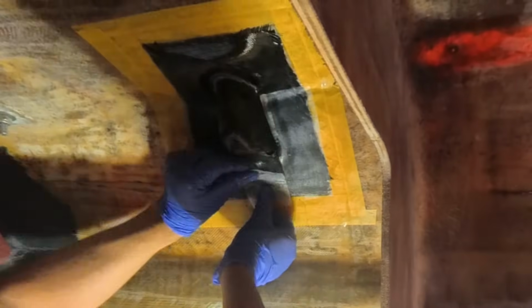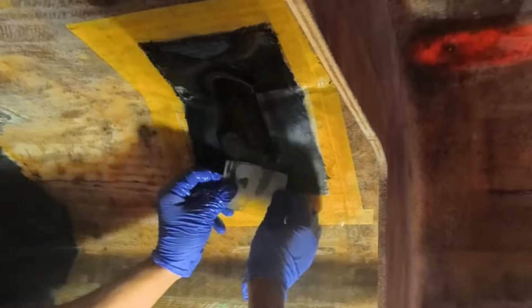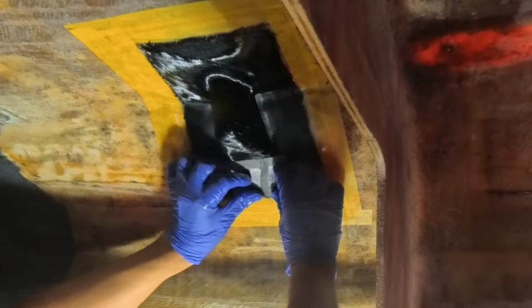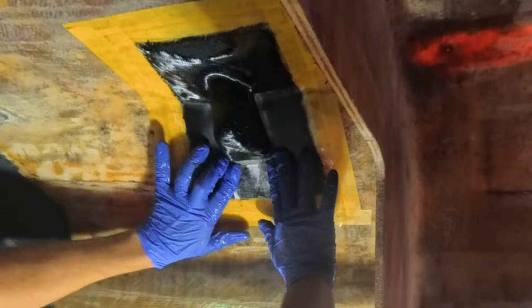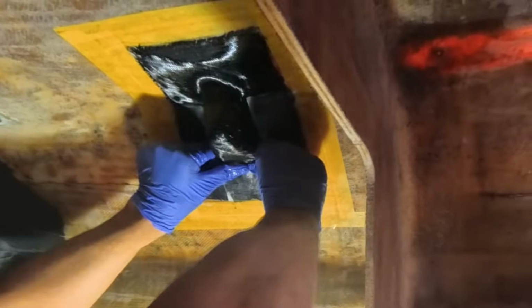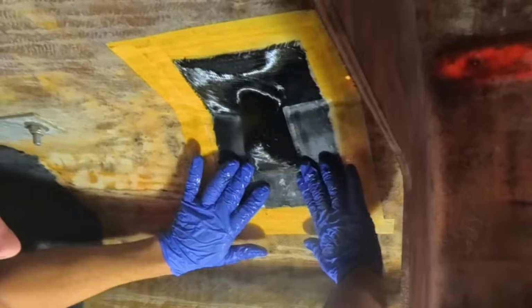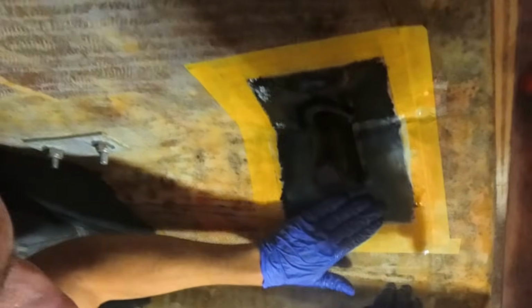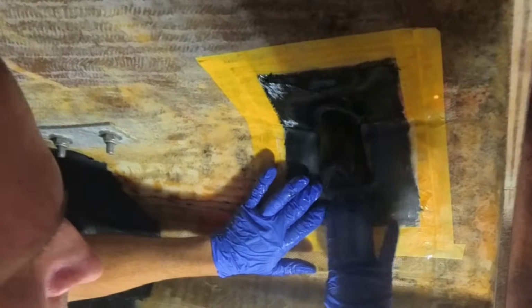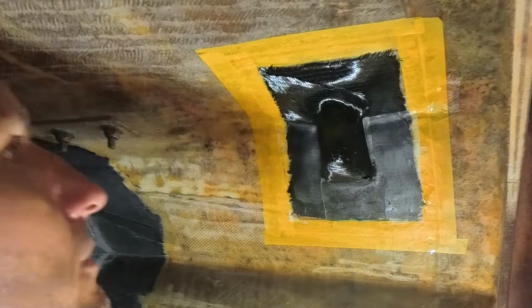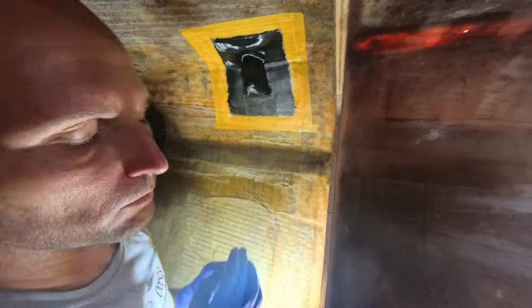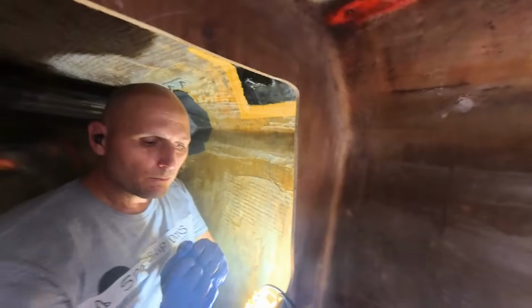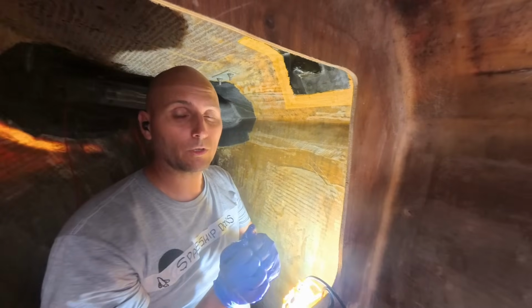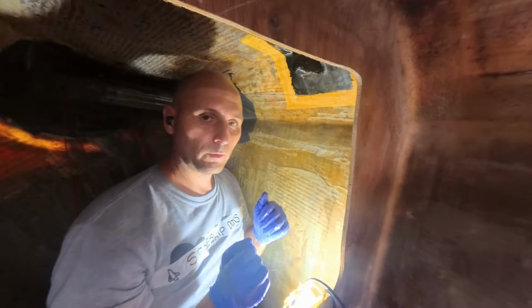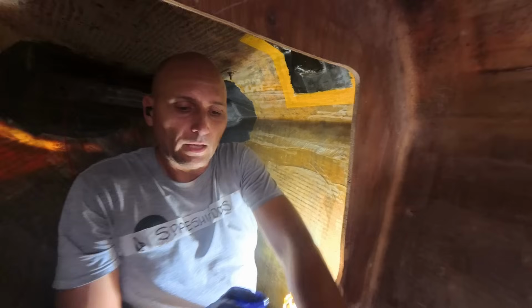It's not best practice. It is definitely not best practice, and there's heaps, and when I mean heaps, there's heaps of literature in regards to peel ply, surface finishes, and preparing them for secondary bonding. And I know a fair bit about this because it was something I was involved in a little bit, and the aviation industry was talking to us a fair bit about it once upon a time, so it is an area I do know fairly well. Simple way to put it, peel ply, whether it's nylon or polyester, either one of the two are coated, and the reason that they are coated is so that they will release from the job, right?